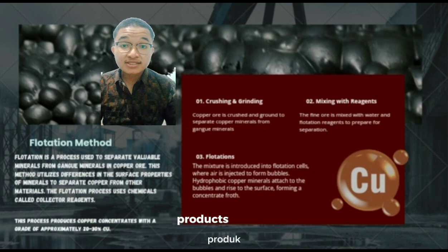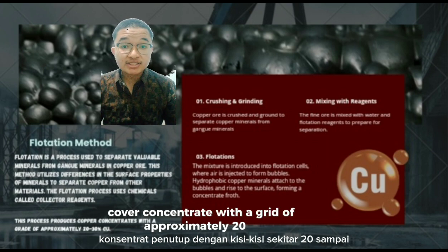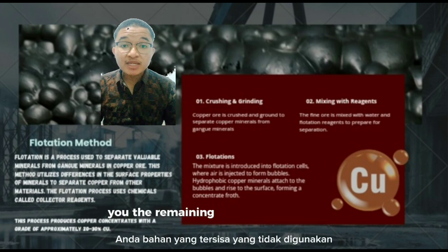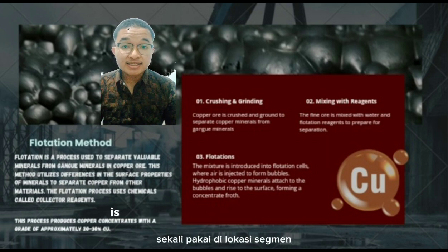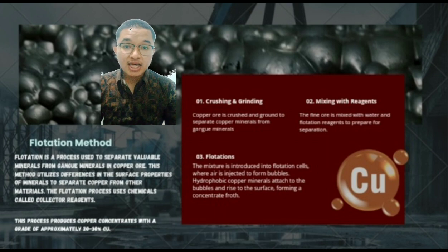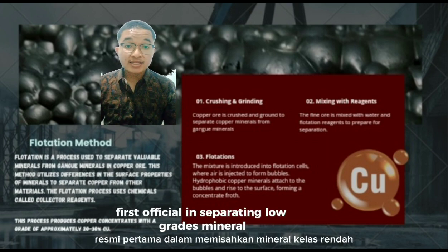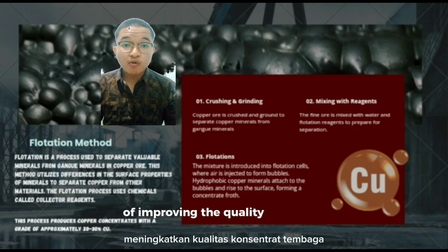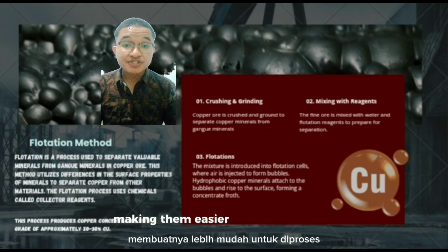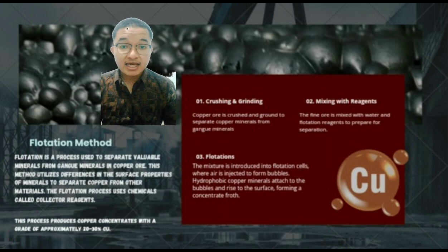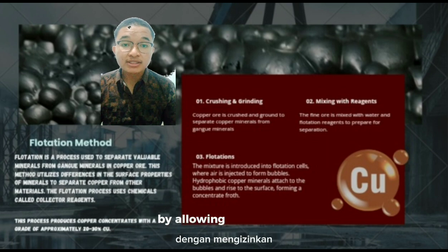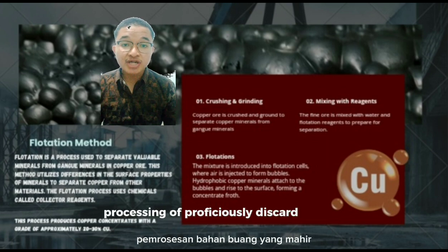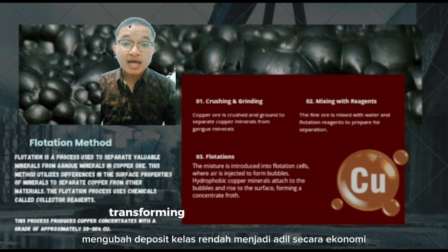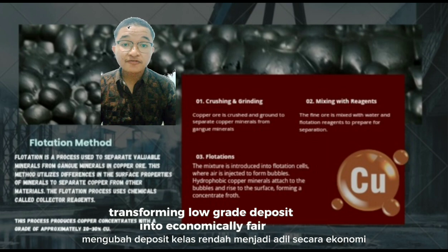Flotation result. This process produces copper concentrate with a grade of approximately 20 to 30% Cu. The remaining material that is not used, known as tailing, is disposed of at a designated location. Advantages of flotation. First, it is efficient in separating low-grade mineral, capable of improving the quality of copper concentrates, making them easier to process in subsequent stages. The process can help in maximizing the recovery of mineral resources by allowing the reprocessing of previously discarded material, thus transforming low-grade deposits into economically viable resources.